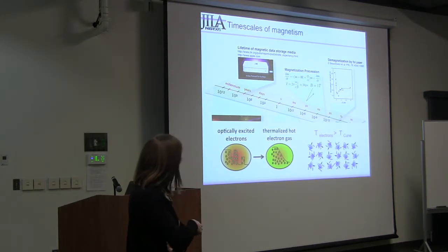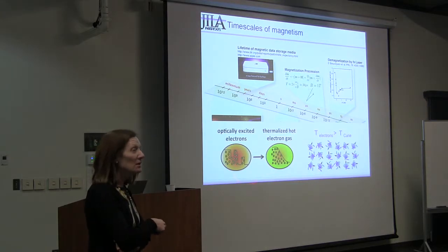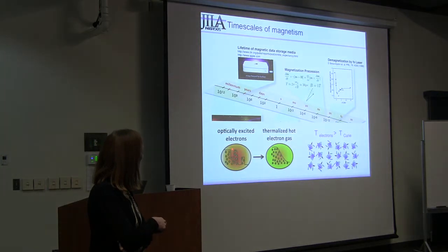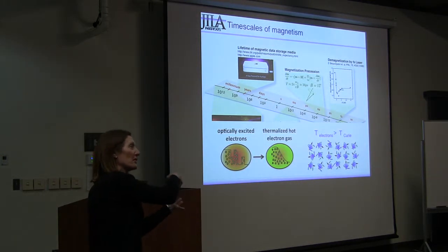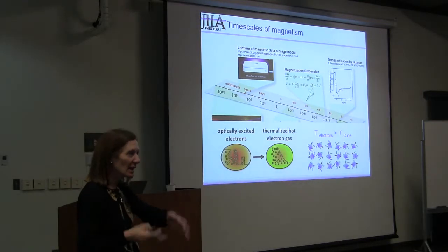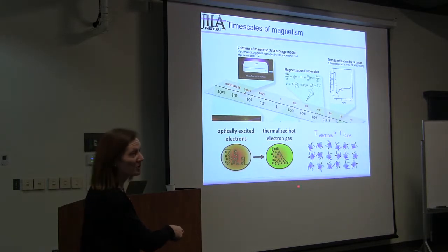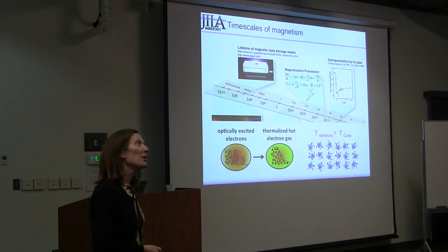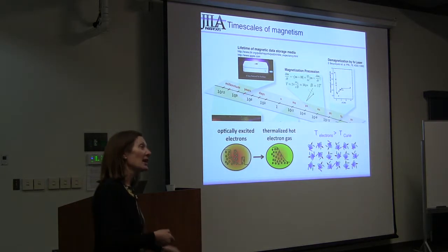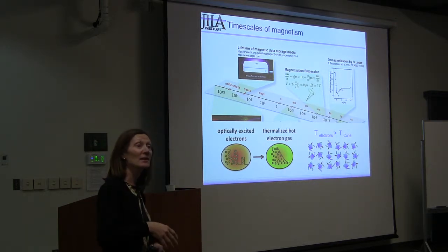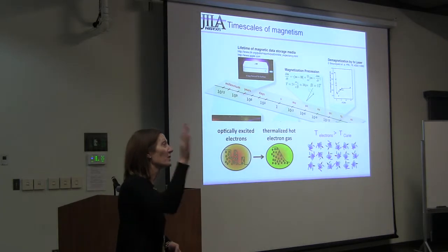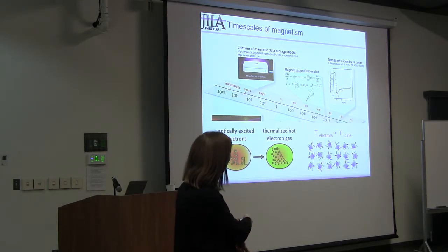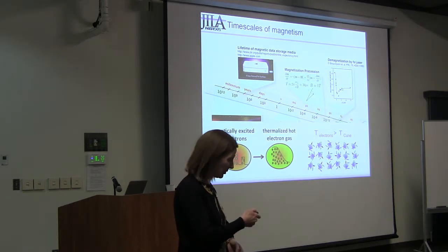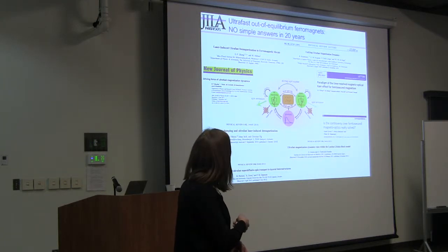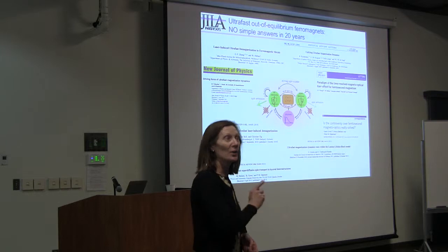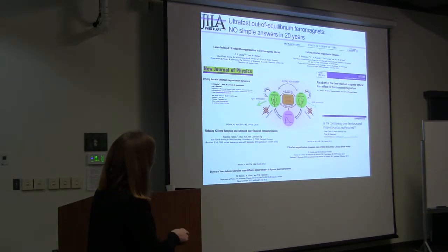So what's going on? Well, we know when you heat a metal with a femtosecond laser that initially you're going to get some lumpy distribution of the electrons, because you're taking electrons from below the Fermi level in the metal to above the Fermi level, and then they need to collide, thermalize, and establish a hot Fermi-Dirac distribution. Because the heat capacity of the electrons is so much smaller than the lattice, the electron temperature can spike well above the Curie temperature while the lattice stays effectively cold. So you do not melt the lattice, but you can still drive the electrons well above the Curie temperature, and then the spin is randomized. But the question is how? And that is 20 years, and we still don't know exactly how.